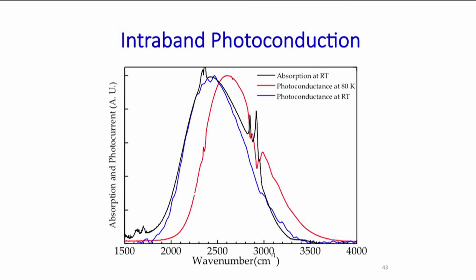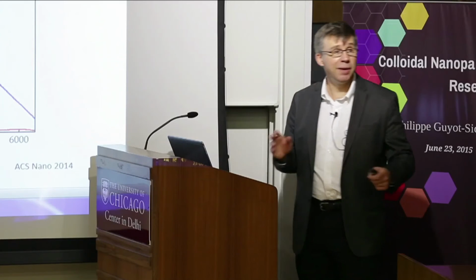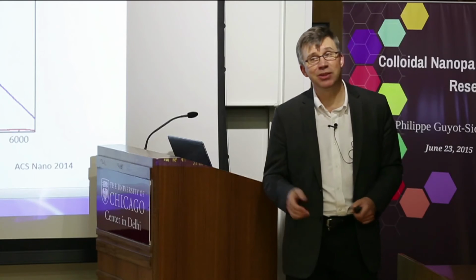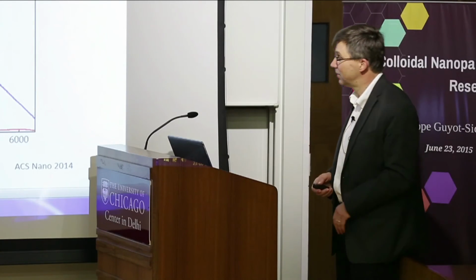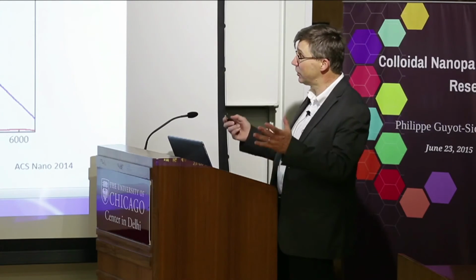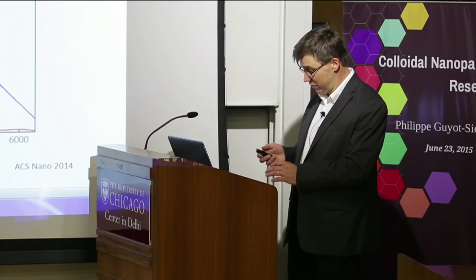And then we cool the system down, and we measure the photo response again, the photocurrent. And now we have this very nice, very low noise response, which is slightly blue shifted. So this was very exciting. It was the first time that we had seen something coming from those intraband transitions, which was the kind of dream I had about 15 years ago of hoping to do, but couldn't do it then.